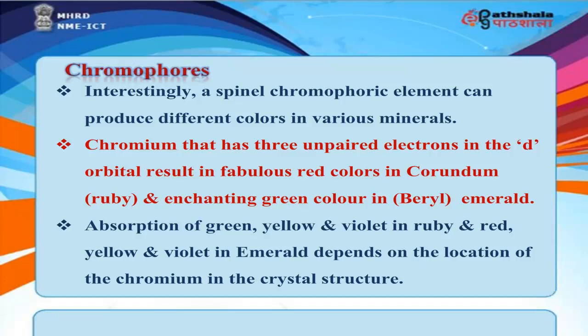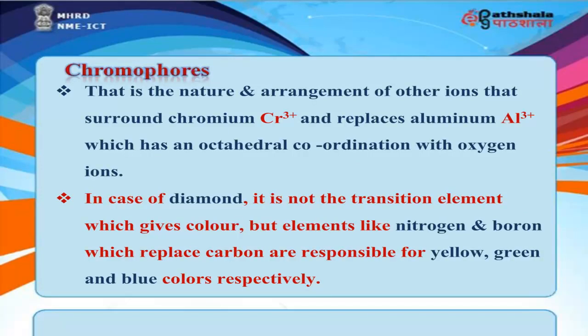Interestingly, a single chromophoric element can produce different colors in various minerals. Chromium, which has 3 unpaired electrons in the d orbital, results in fabulous red color in corundum, ruby, and enchanting green color in beryl, or emerald. Absorption of green, yellow, and violet in ruby and red, yellow, and violet in emerald depends on the location of the chromium in the crystal structure. That is, the nature and arrangement of other ions that surround chromium 3+, which replaces aluminium 3+, which has an octahedral coordination with oxygen ions. In the case of diamond, it is not the transition element which gives color, but elements like nitrogen and boron, which replace carbon, are responsible for yellow, green, and blue colors respectively.